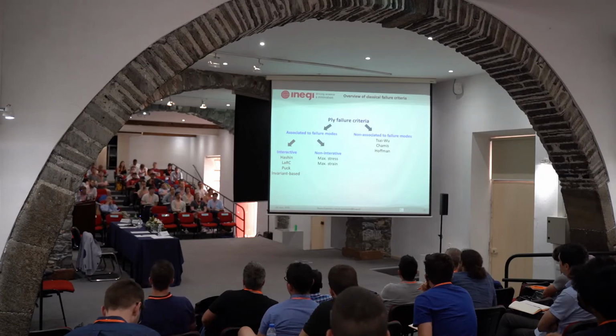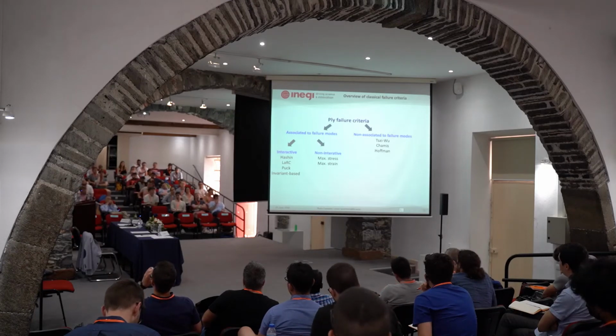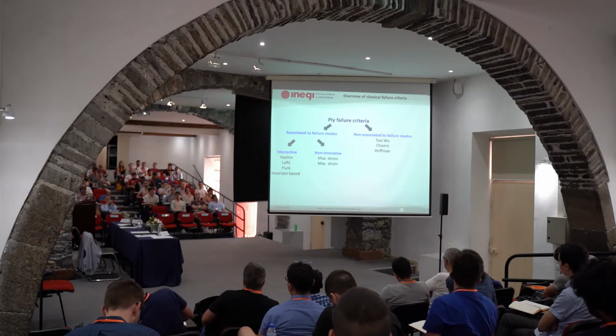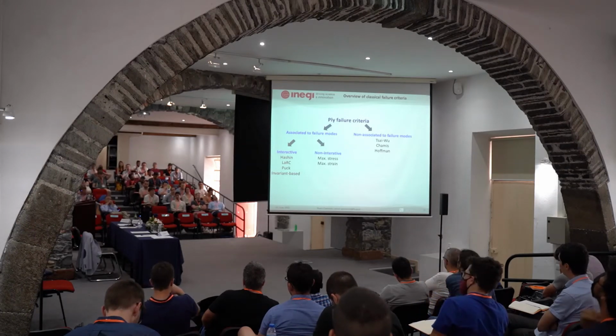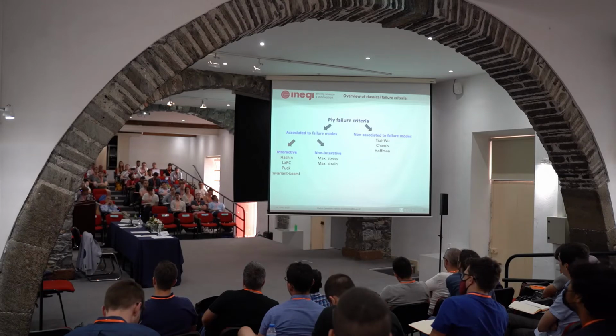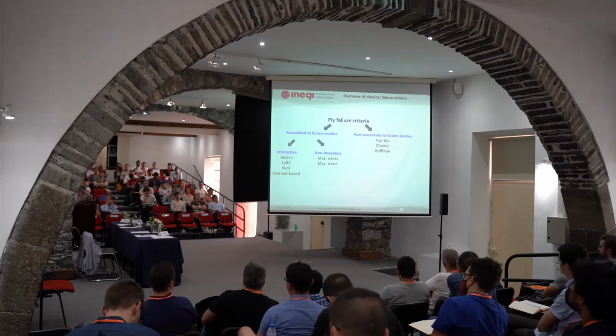Now, of course, what we want to do, there are two things. The first thing is, of course, failure criteria will give you the stress or strain conditions that will trigger the first crack, okay? Now, if you have a UD composite, that will represent the last ply failure as well. It will represent the failure of the specimen.